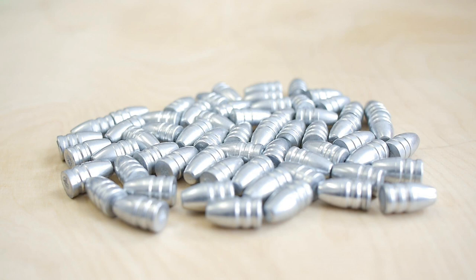From what I can tell you now is that casting zinc bullets is no magic. If the mold is hot and the zinc is hot enough, you can cast zinc bullets just like you are used to casting lead bullets. I water quench those zinc bullets — not to harden them, but because of shrinkage, so resizing is not that hard later.